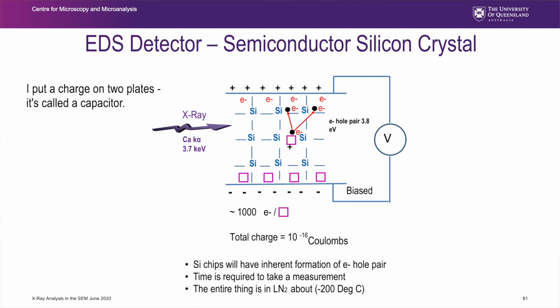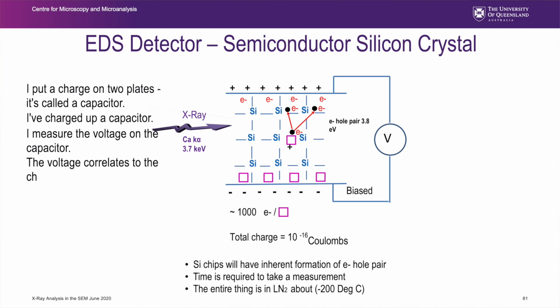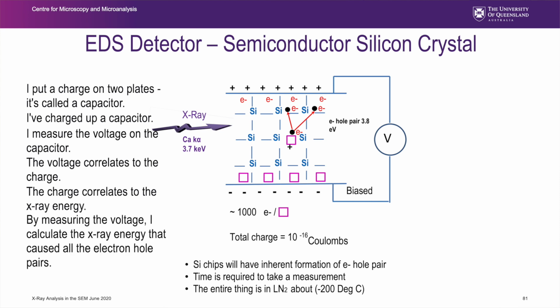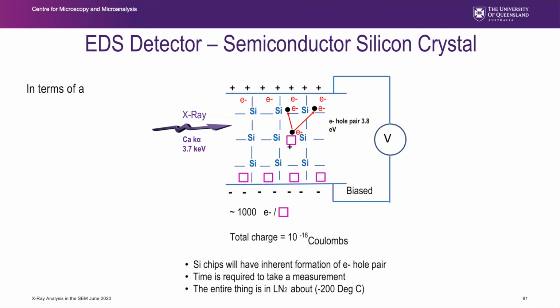In the end, I put a charge on 2 plates. In normal electrical terms, that's called a capacitor. I've charged up a capacitor. What do I do? I measure the voltage on that capacitor. The voltage correlates to the charge, which correlates to the X-ray energy. By measuring the voltage, I calculate the X-ray energy that caused all the electron hole pairs. Of course, I've only got about 1,000 electrons there in terms of absolute charge. That's a very, very weak charge.